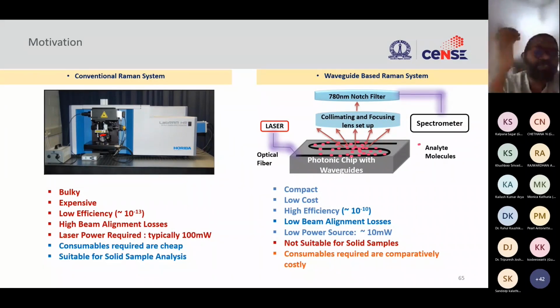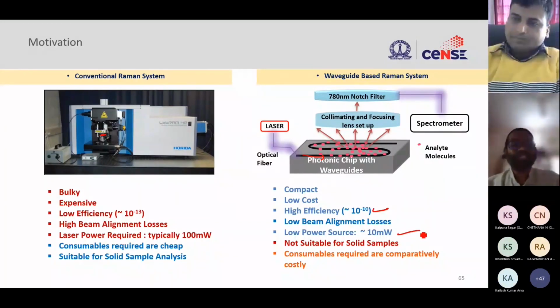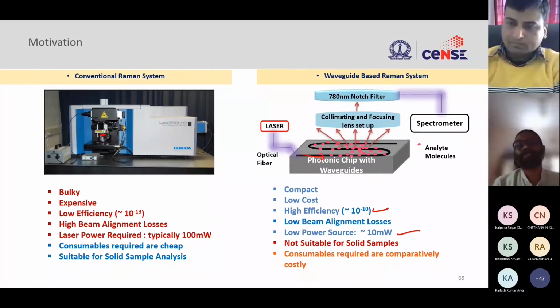Then we thought, we have these waveguides where you can confine the light. Is it possible to generate Raman signals from these integrated waveguides? You have waveguides where the light is propagating, and whatever analyte we have, you can throw on top, and the propagating light will interact with this analyte, and based on this interaction, you can generate Raman signal. And these efficiencies are 3 orders of magnitude higher than what you get from a simple conventional Raman system. And you can actually use very little power. We're talking about tens of milliwatts, while in a simple Raman setup you need 100 milliwatts or so.